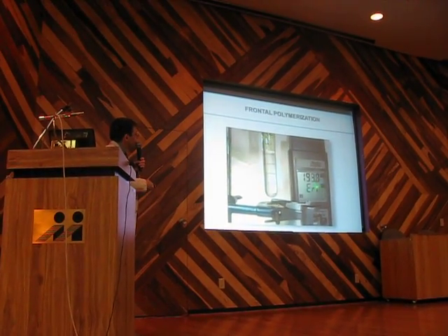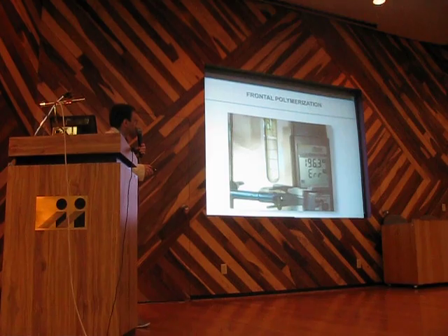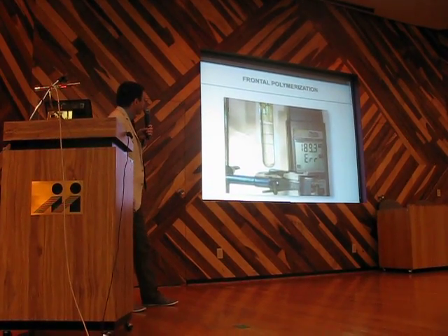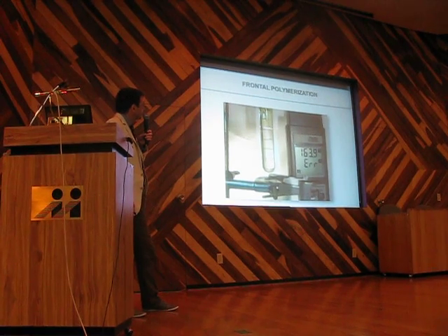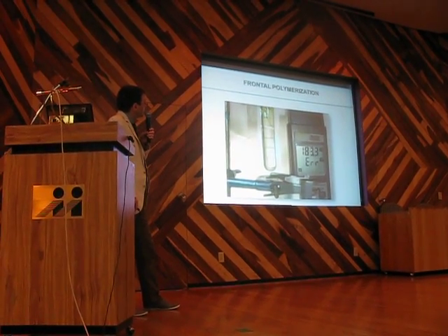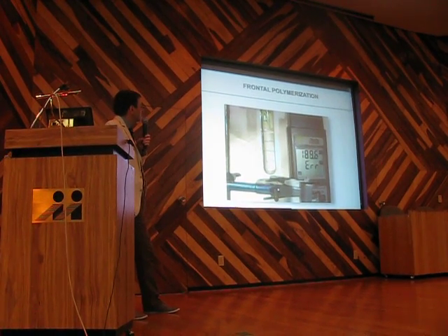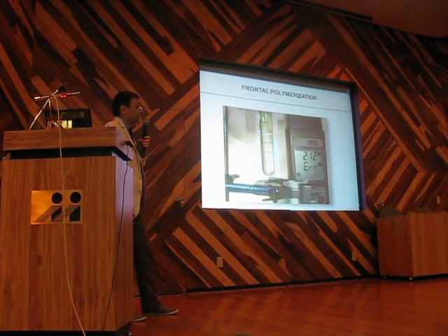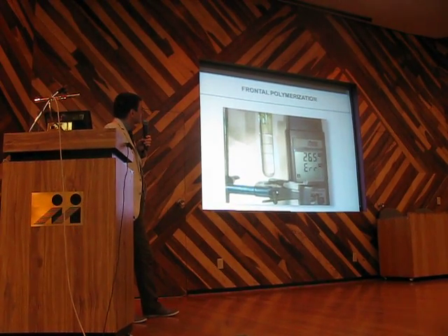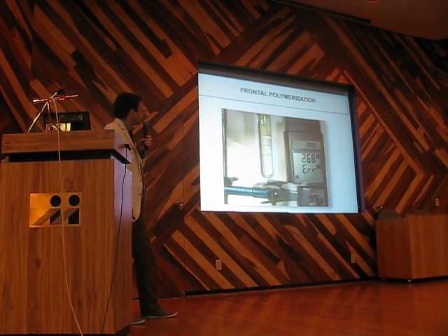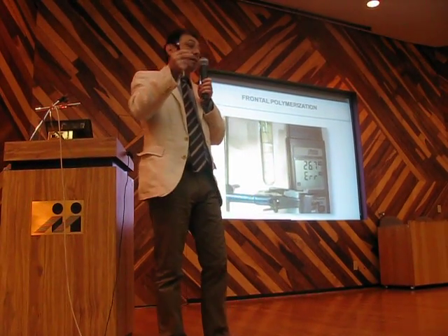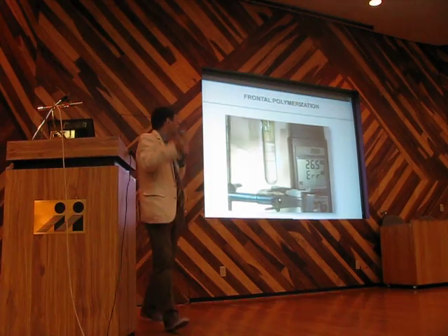And in this case, the system reaches more than 200 degrees. I don't remember how much now, we discover it in a moment. And then I stop it. Okay, 270 degrees more or less, without heating it, apart from the ignition.